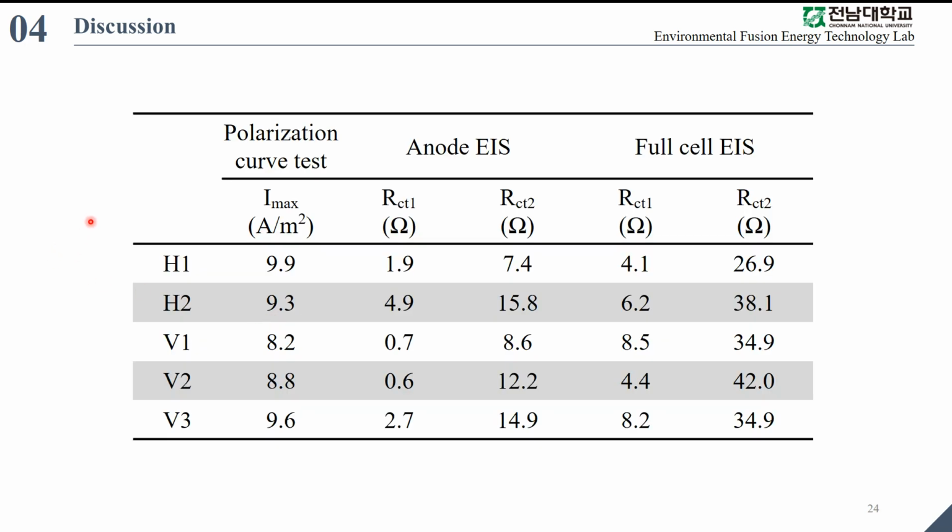The charge transfer resistance contains an anodic resistance related to the transfer of electrons and charges in respiration of the anode biofilm community. As the distance between the 2 electrodes decreased, the amount of current increased and the energy obtained by the anode biofilm increased. In this case, decreasing electrode distance could make respiration of anode biofilm faster so that anode charge transfer resistance could be reduced.